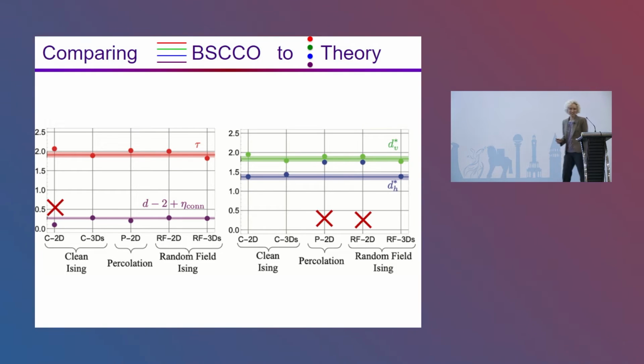So what kind of inferences can we make based on this? Based on the paraconductivity exponent, we can rule out the clean Ising model in 2 dimensions. So this exponent is not matching. I know they look close on the graph, but this is the 0 line. And so this is about 0.2, and this is about 0.1, and this is about 0.26. And so they're outside the error bars of each other. So it's not matching a clean Ising model. It's also not matching percolation.